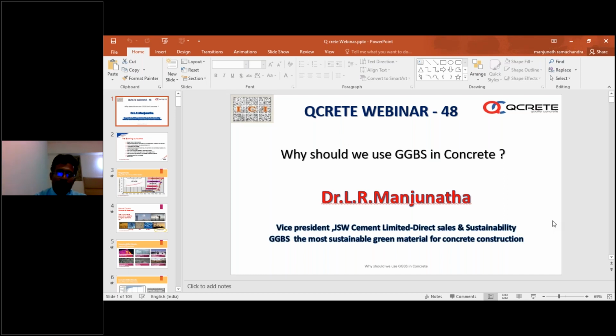It depends on the cement content, the cementitious content, and the durability parameters. Mainly, let us say you only require strength, M60 grade concrete. I think that with 35 to 40% you can use it. But somebody says my RCPT value should be low, my water absorption should be low, my water penetration should be low. With these conditions, strength becomes the second criterion, but we can specify 56-day strength for M60 grade concrete, not 28 days. So when you want durability, it demands higher replacement of GGBS. When you only require strength, then you go with a lesser replacement of GGBS.